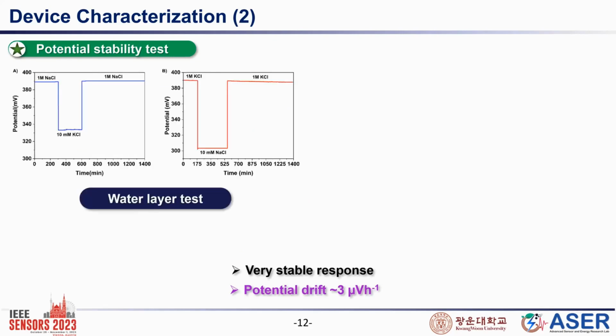So then we go for another characterization of our ISE, that is the water layer formation test, actually, as suggested by Pires. This result indicates a very stable response when we change our target analyte to another interfering analyte. And we have calculated the potential drift. For potential drift we have got a very excellent value, that is only 3 microvolt per hour. So that indicates its viability for clinical grade.